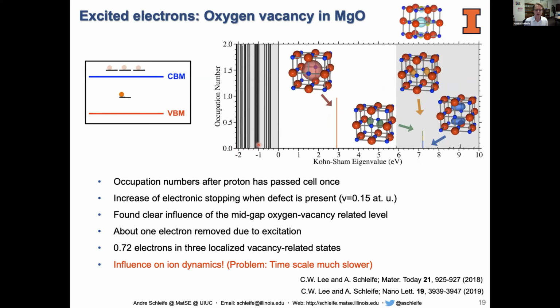Everything at lower energy is valence states. Everything at higher regions, which is gray here, is conduction band states. Here's your defect level. After the proton moved through it, it's singly ionized. One electron is gone. That's what we see here in the occupation number. And then this analysis tells us where the electron went.